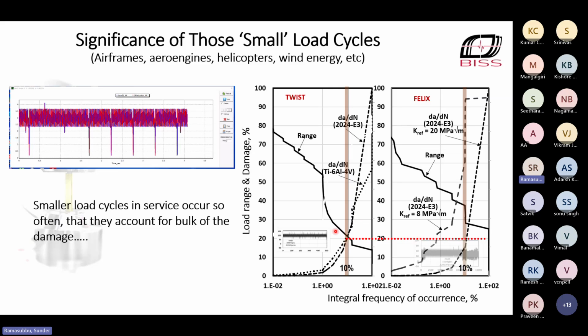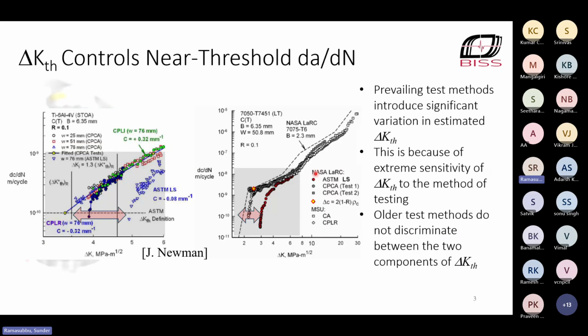The same thing holds for helicopters, and I would imagine it applies to a lot of vehicles that move and rotate. So small load cycles matter a lot. If you look at the fatigue crack growth curve, where the vertical axis is the growth rate and the horizontal axis is delta K, the lower growth rates probably matter most, because most of the fatigue life is spent at low rates, owing to small crack size, or because most of the load cycles that push the crack forward are quite small in service.